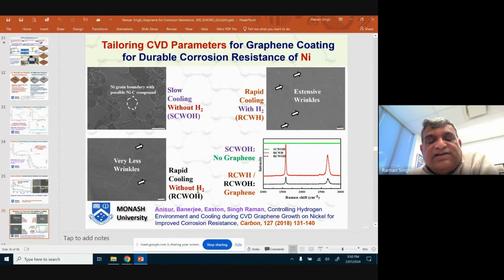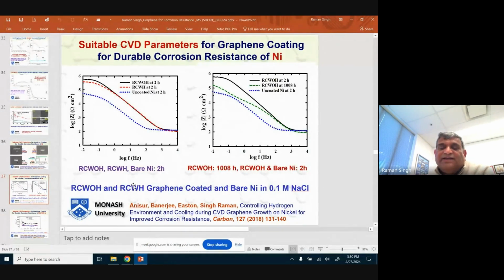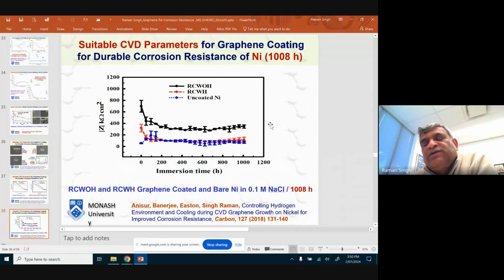So this is the particular condition in which we could develop very good quality graphene, and that graphene gave very long-term corrosion resistance. As you can see, it is statistically proven data that graphene developed with rapid cooling and without hydrogen gave very good corrosion resistance that lasted for over 1,000 hours. That was the entire test duration. Whereas if your graphene development conditions, the CVD parameters, were not correct, if you are doing rapid cooling with hydrogen and graphene quality was not good, then the improvement was not good. So here you have statistically proven data for graphene giving very good corrosion resistance to nickel in sodium chloride solution, a highly corrosive seawater type of solution, for 1,000 hours.